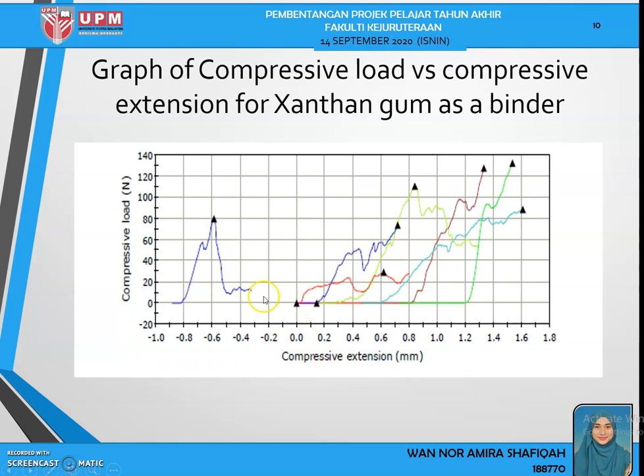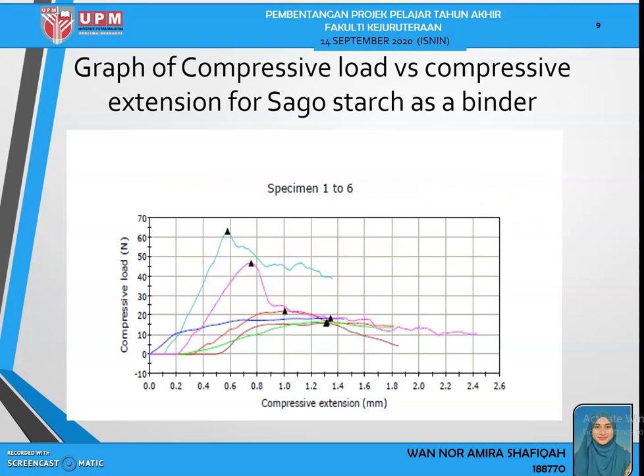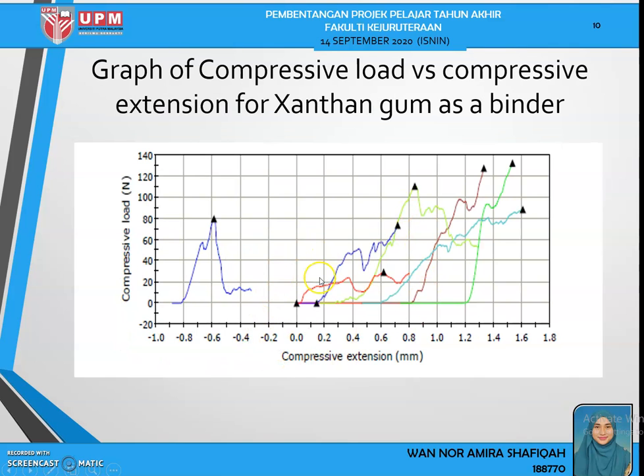So this is for the xanthan gum. It shows that the tablet cannot sustain even when the load is applied. So as a conclusion, by comparing these two graphs, it shows that when using sago starch as a binder, the tablet can sustain longer over a range of compressive strain before it fails. The tablet prepared using xanthan gum is strong but fails abruptly.